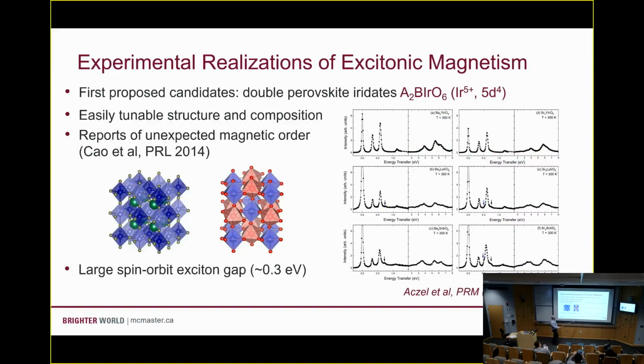And actually, if you go out and measure a bunch of these different materials, you can see here we've got a variety of different A sites, barium, strontium, lanthanum as well, and B sites. Here you can tune the crystal structure from cubic to monoclinic, so you can introduce all these distortions. And maybe it's hard to tell, but there's almost no difference between any of these. Okay? So the energy levels look the same. They're very insensitive to any structural details.